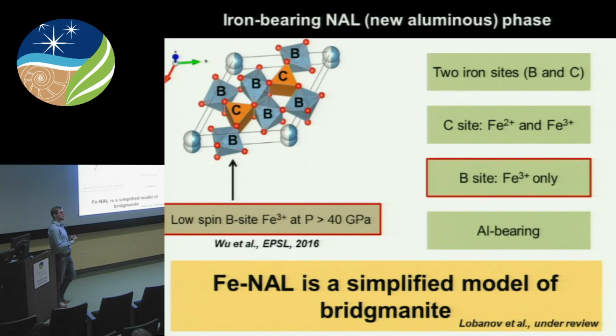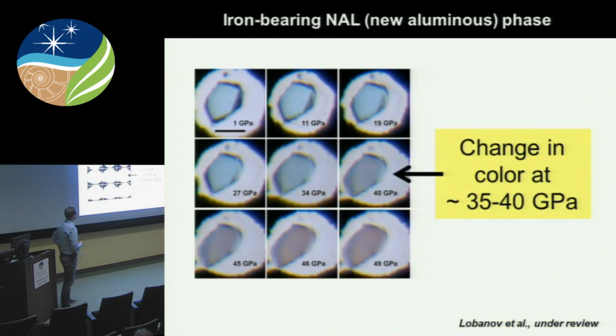And one example is NAL, and NAL simply stands for new aluminous phase. So this mineral can incorporate iron also into two different sites. The octahedral B site incorporates exclusively Fe3+, which undergoes a spin transition at 40 GPa, as is documented by a Mossbauer study. So this mineral gives us a model for a spin transition in Fe3+ sitting at an octahedral site, and therefore it may be used as a simplified model of bridgmanite.